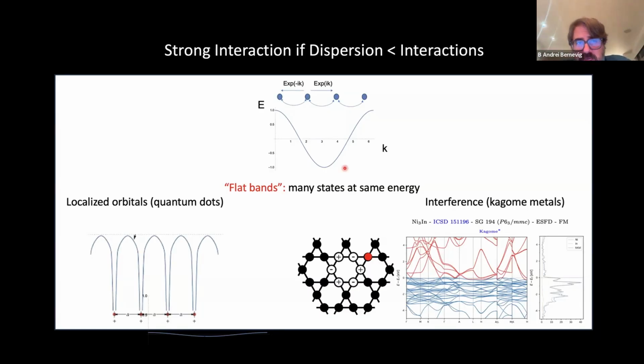Now, there are several ways of making the kinetic energy small. One of them is by just putting the electrons in a very large negative quantum well, or potential, so they just sit there and they don't move. That's not a very interesting way of making the kinetic energy small, but there are other ways which are more interesting. For example, in these Kagome metals, where the electron center sits in the Kagome site, which is this one, you can clearly see the presence of what we call flat bands.